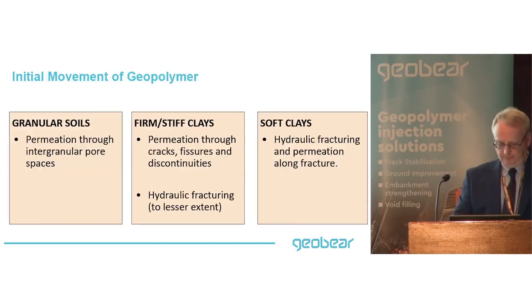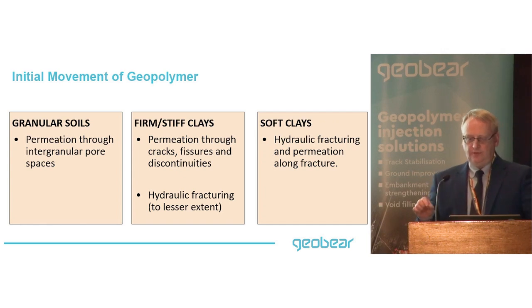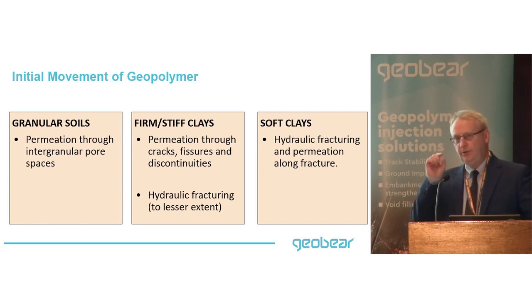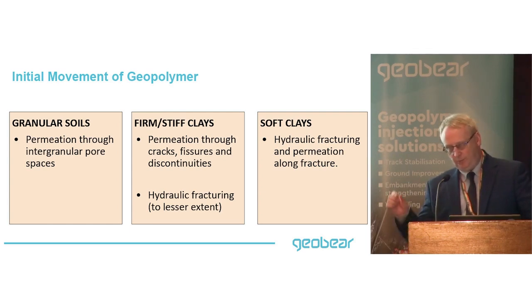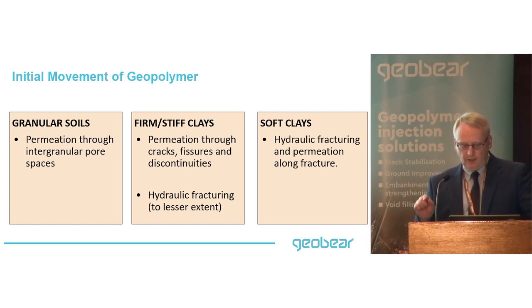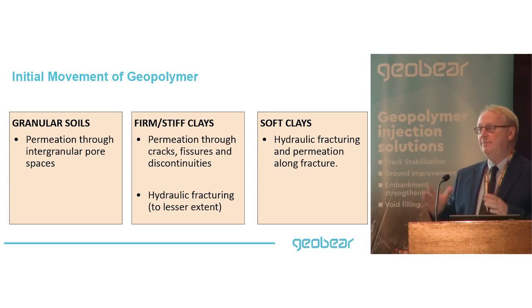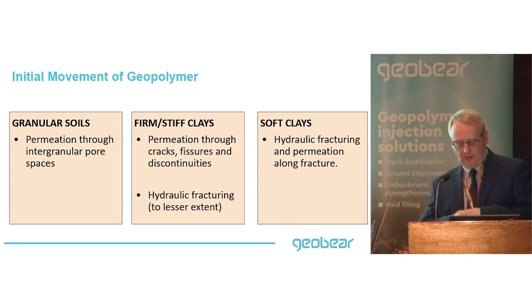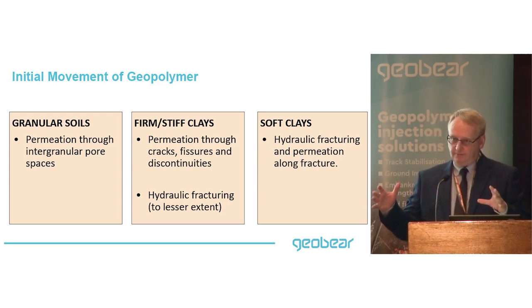At the point of injection, when we do our treatment, we drill a small hole, 15 to 16 millimetres, and put an injection tube into the ground, through which we inject the polymer under pressure. When you have a granular soil, like a gravel, the initial permeation is through the intergranular pore space, flooding the space between particles. That's called permeation.